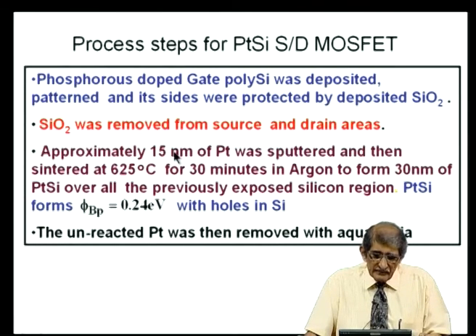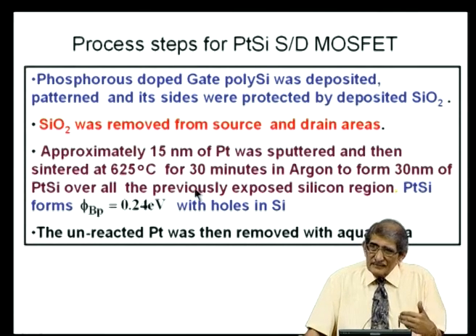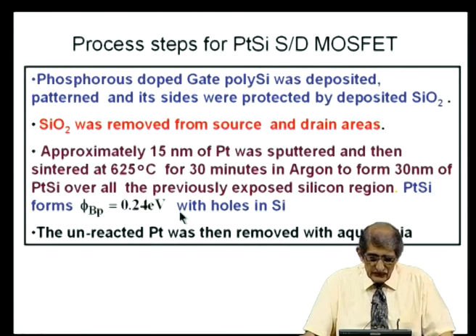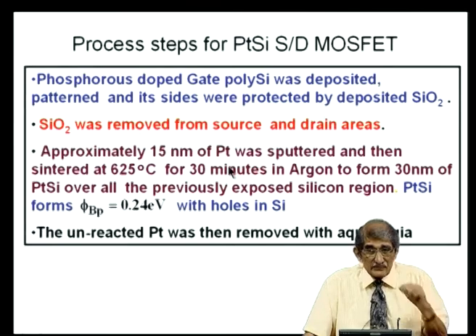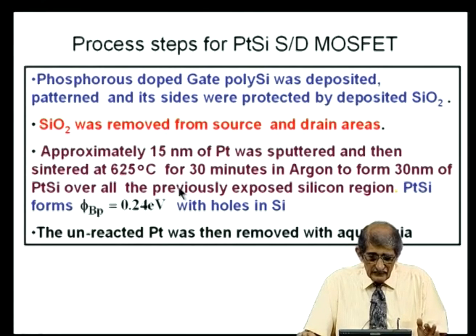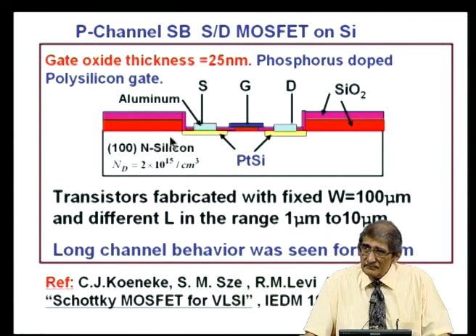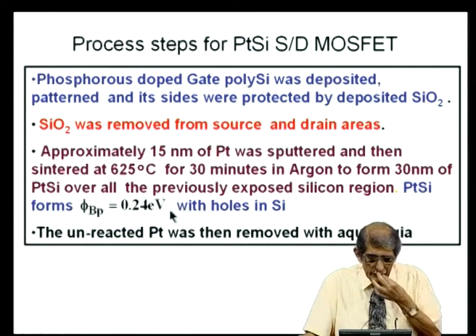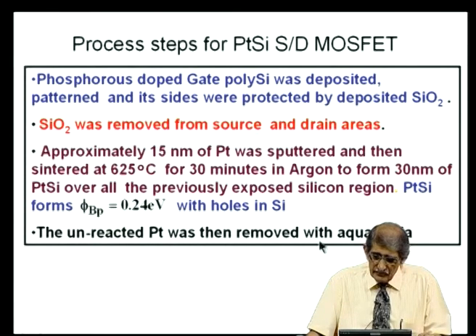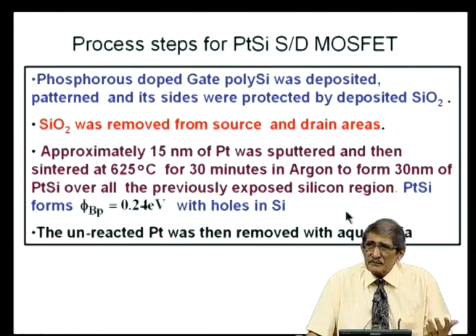Approximately 15 nanometers of platinum was sputtered and then sintered at 625 degrees centigrade for 30 minutes in argon to form platinum silicide. In fact, it consumes silicon, which is why it is shown getting inside the silicon. You get about 30 nanometers of platinum silicide over all the previously exposed silicon regions. Wherever silicon is exposed, you get platinum silicide. Other places, there is no silicon, so no platinum silicide. Then the unreacted platinum was removed by aqua regia, or you can use reactive plasma etching.